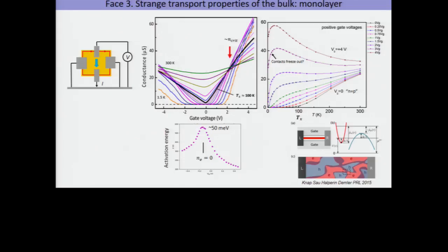It is a two-dimensional semimetal. What should it do? Graphene is well known, but what about others? So these are measurements of the bulk conduction in a monolayer, the one on the left here. The way we get at the bulk is we ground the edges. We apply a bias at the top there, and measure the current out at the bottom there, and we stop the edges from carrying any current by grounding them. If someone's got a better idea for how to do this, please let me know, but separating edges and bulk is a tricky business. Anyway, this is what we do at the moment.